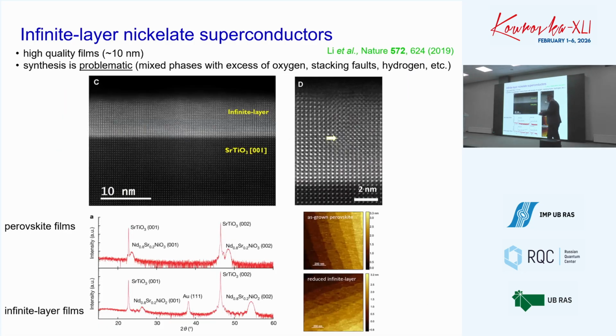Of course, these materials, these thin films, must be as clean as possible, and this is a very nice result. Superconducting thin films grow on strontium titanate and are covered again on top with strontium titanate to make them more homogeneous, because these thin films are somewhat metastable. This stabilizes the crystal structure of these materials, but you may see that the synthesis is quite problematic. You might see some kind of defect structure.